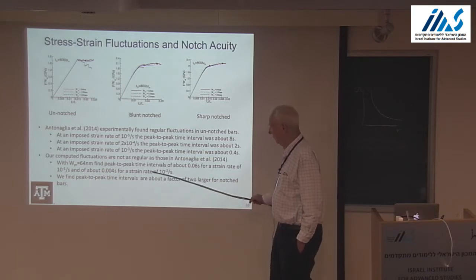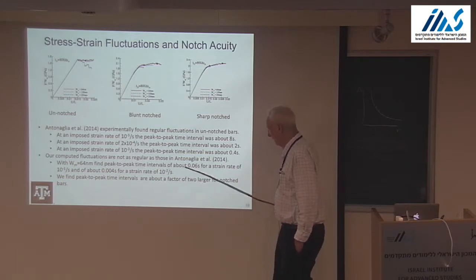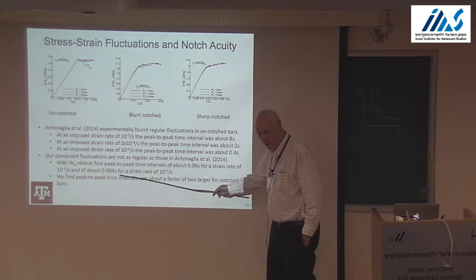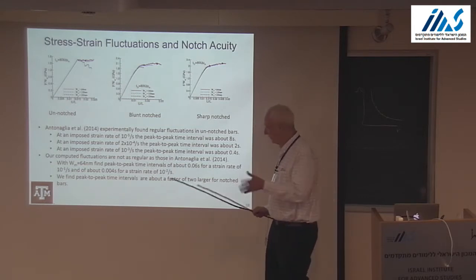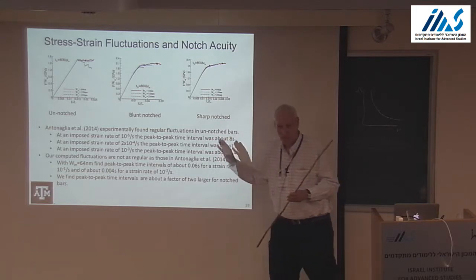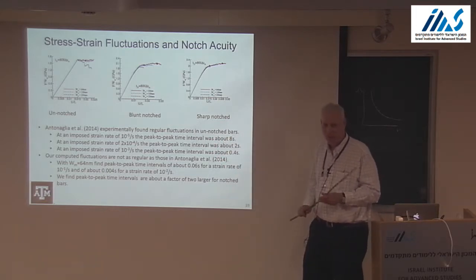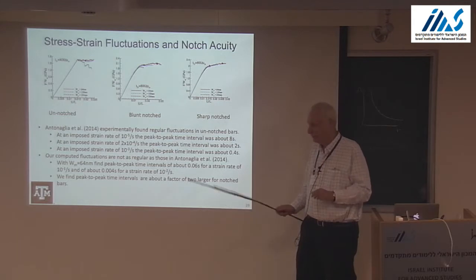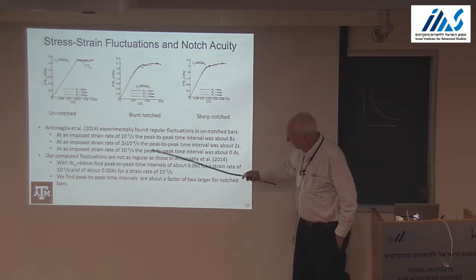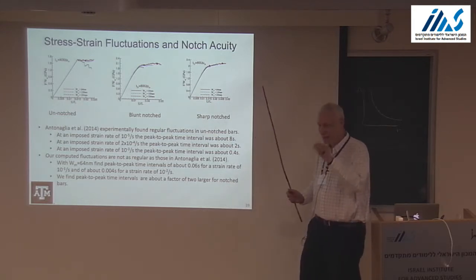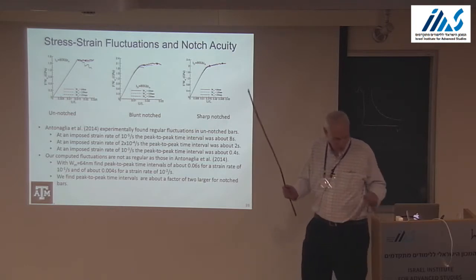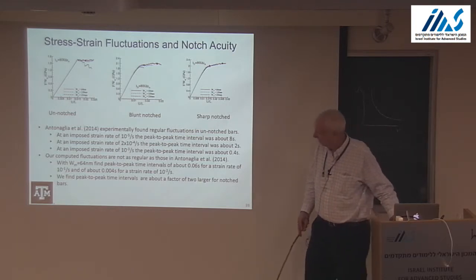So we go from about 0.06 seconds to 0.04 seconds. So if you were to scale this up linearly, we're about a factor of 3 or 4 off from the experimental, but the trends are the same. So again, I think the time scale of these oscillations or fluctuations is very important.